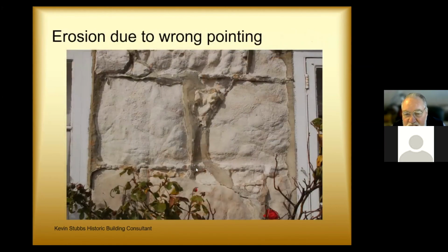And again, on the island, the hard chalk clunch has been used here for this 17th century vernacular building, which survived beautifully for 300 years, and then somebody repoints with a cement mortar, and the chalk clunch blocks are decaying rapidly.